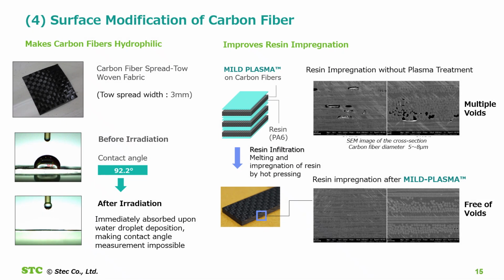The last one is carbon fiber. The left side shows that mild plasma makes carbon fibers hydrophilic. Before treatment, the contact angle is 92.2 degrees. After treatment, the water droplet is absorbed immediately, to the point that contact angle measurement becomes impossible. That improved wettability leads to better resin impregnation. On the right side, the cross-sectional SEM image shows the difference clearly. Without plasma treatment, you see multiple voids, and after mild plasma treatment, the structure becomes much more uniform and free of voids.